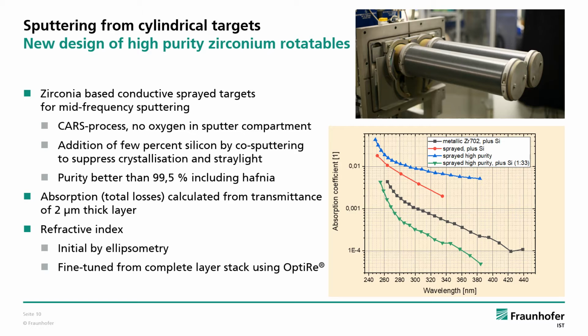The high purity target, together with the addition of only a few % silicon by co-sputtering, suppresses the crystallization and reduces stray light losses of the layers. This gives the low total losses of the green line, which is the process we used. With a similar deposition rate, but no silicon addition, there is a huge effect from crystallinity, which was determined by X-ray diffraction and can be seen in the blue curve.